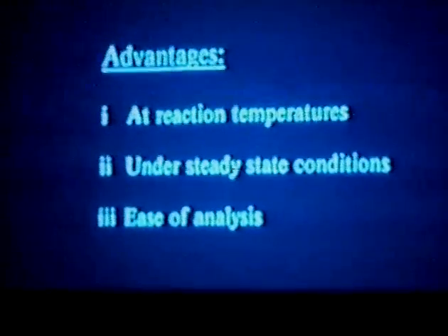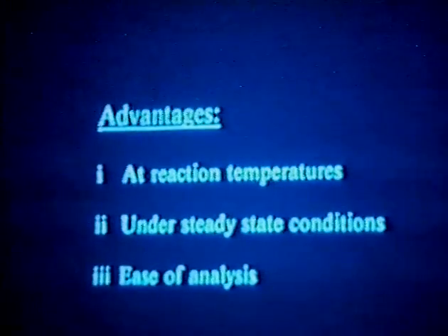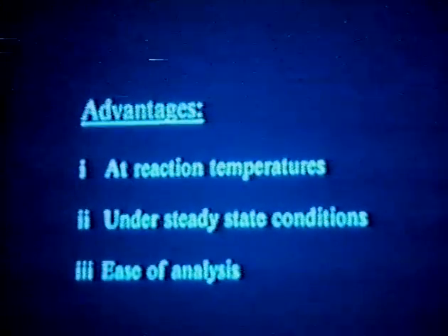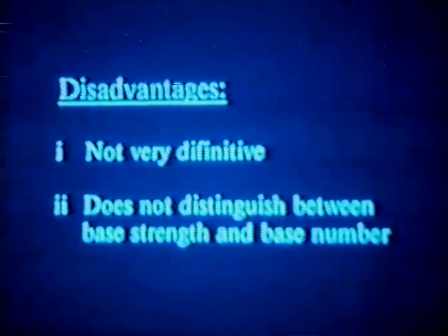The characterization of these zeolites is kind of an elusive thing to do as far as determining the strength of the base or the acid site. We looked at isopropanol decomposition in a parallel reaction pathway to acetone and hydrogen. Looking at this as our base indication, we're looking at acetone rate versus propylene rate. A high acetone rate and hydrogen is indicative of strong base selectivity. The propylene is usually indicative of Bronsted acidity by elimination. However, there's considerable evidence to show that propylene can be formed over solid bases as well, and we'll elucidate on that later in the talk.